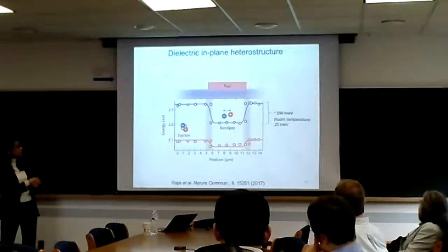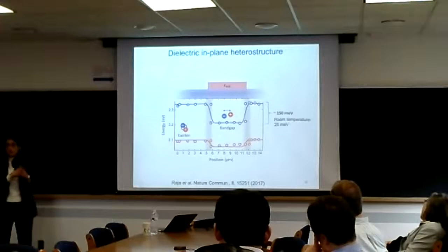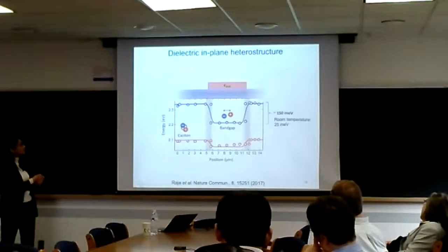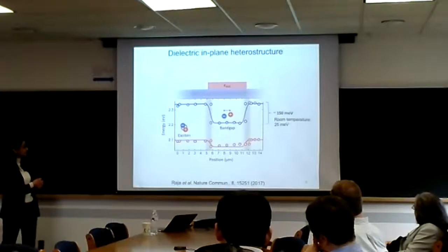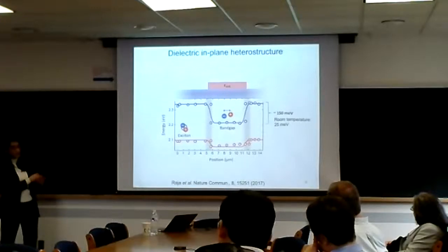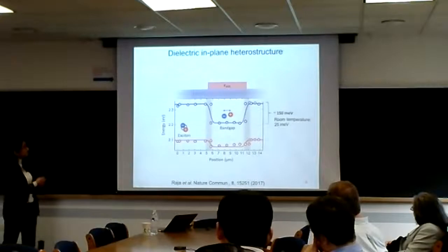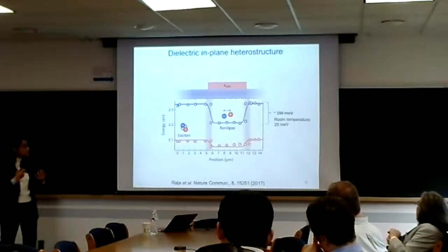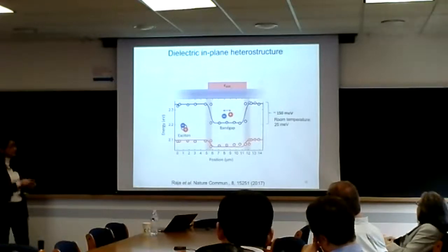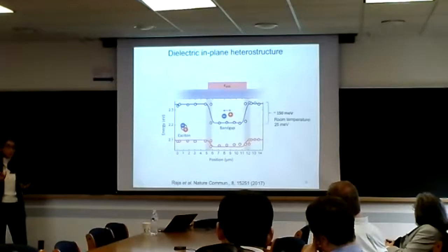So to summarize, what I want you to take away from this is that if you have a monolayer of a 2D material and you were to place this graphene on top, for example, or an external dielectric environment, you can create a potential well in this system without really changing anything in this material itself, ostensibly. And this can be an effect on the order of 100 meV. The limit would be close to the binding energy, and also this change will scale with the binding energy.